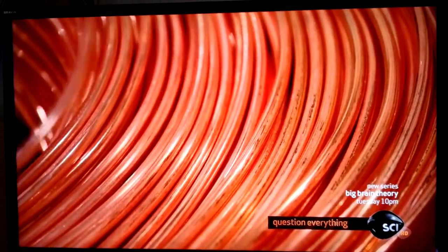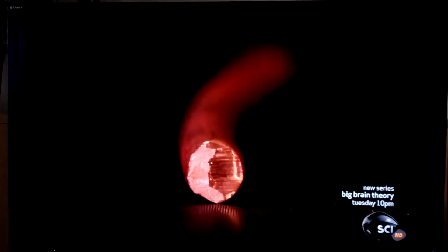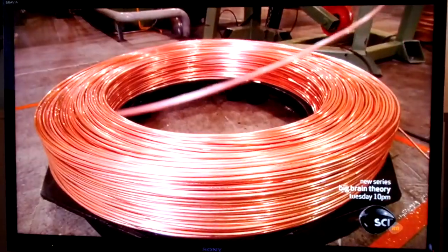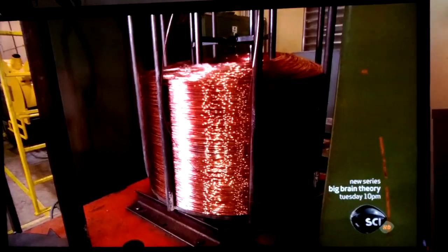The copper rods are 5/16 of an inch thick, a standard size for raw stock copper. It's far too thick to fit into the cables. To thin the copper, it's passed through a series of 9 metal dies that draws or elongates the rod into a longer, thinner wire. Wire drawing fluid is constantly pumped through the machine to keep the dies from wearing down and give the copper a smooth finish. Each die reduces the diameter of the rod by 20% until it's just 8/100ths of an inch thick. For every 350 feet of copper that goes into the machine, more than 5,000 feet of wire comes out.